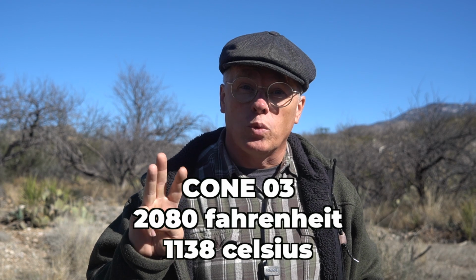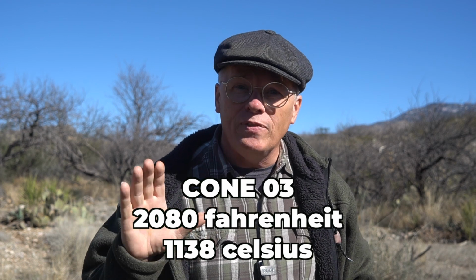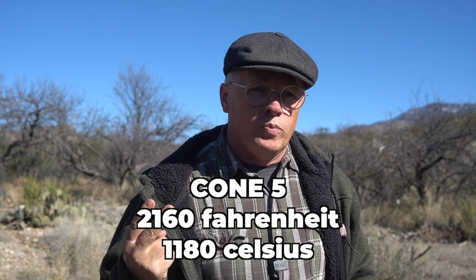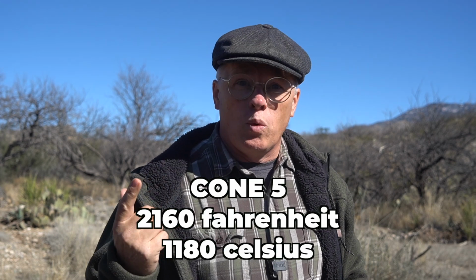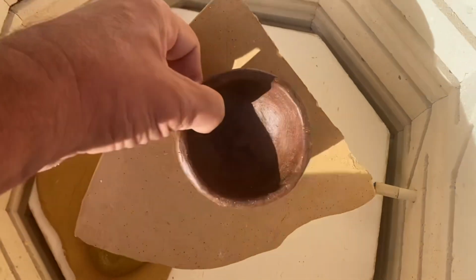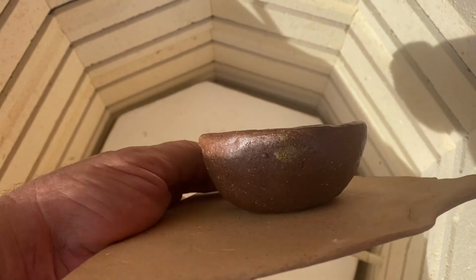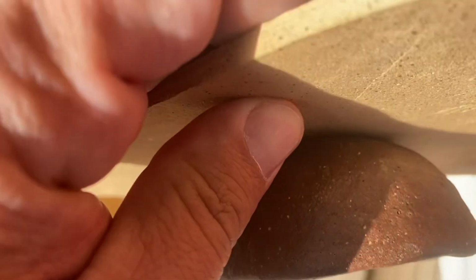So first of all, from the first firing, we know that all three of these clays work fine at that first temperature. We can safely fire these clays at this temperature. For the second temperature, however, we know that the double adobe white doesn't really work at that temperature. It should be backed off quite a bit, probably fired more at the first temperature. We also know that the other two clays, Old Sonoyta Highway and the Mogollon Dream Clay, can be fired at this higher temperature, but it's a little bit too hot. As we saw, they stuck to the kiln furniture. So again, maybe back that off just a little bit or fire to the first temperature.